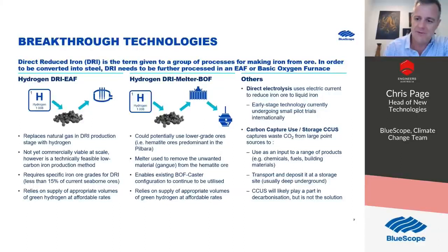Now, the fundamental change that occurs here with the iron ore is that either carbon or hydrogen strips the oxygen atom off the iron ore. Both of those elements, carbon and hydrogen, can reduce iron ore to iron. There are fundamental differences in those reactions, however. When you use carbon, the chemical reaction is exothermic, so it actually produces heat. When you use hydrogen, it's endothermic, so it actually absorbs heat.